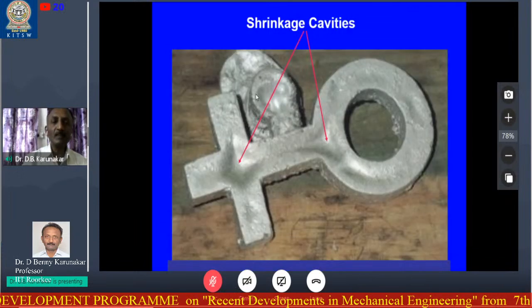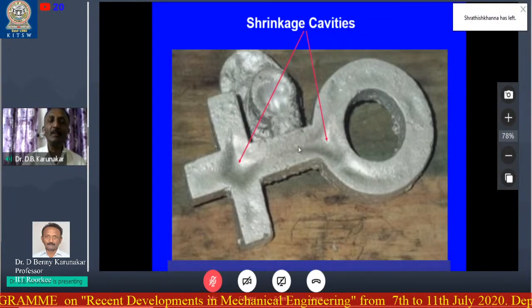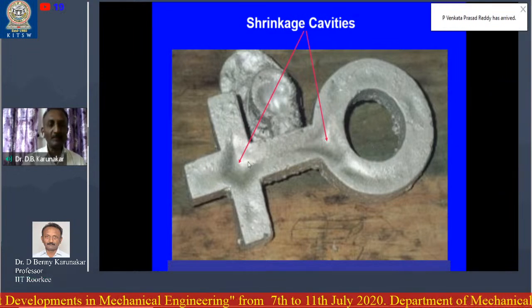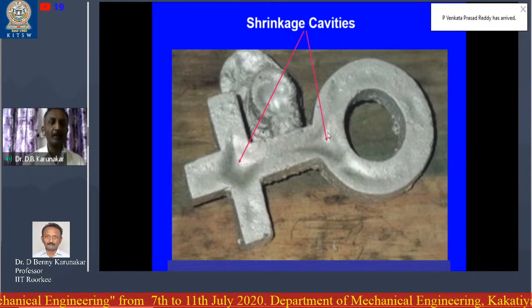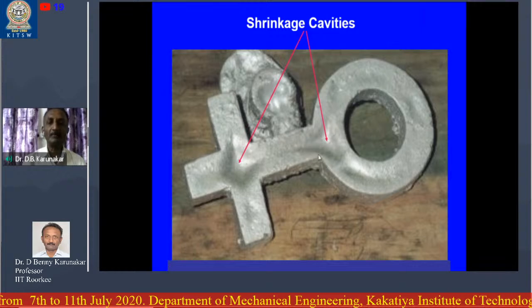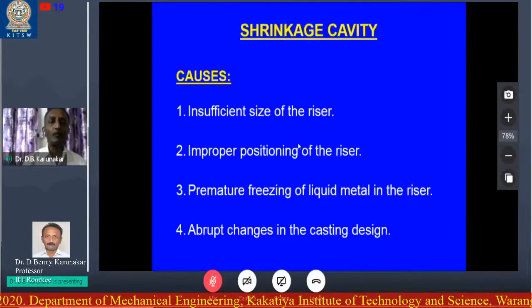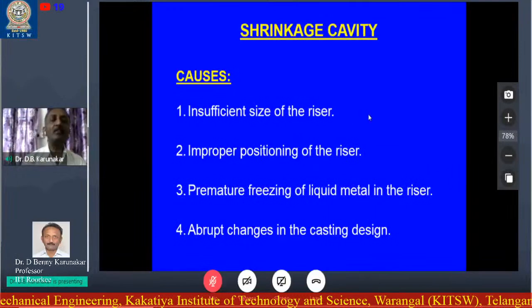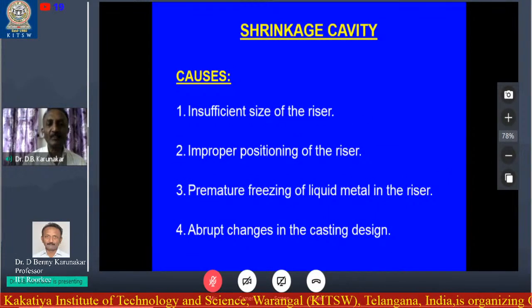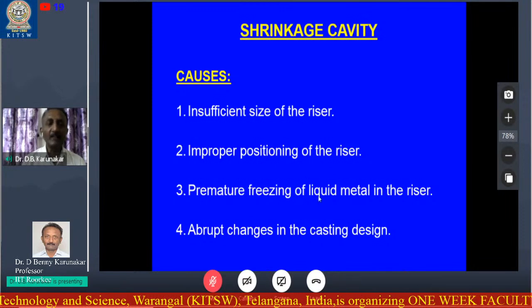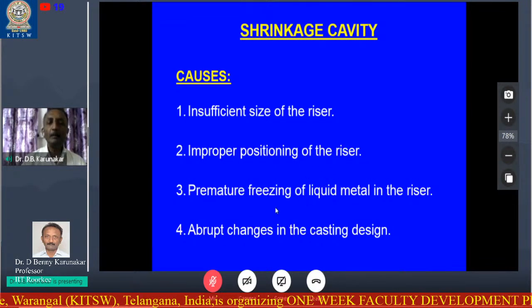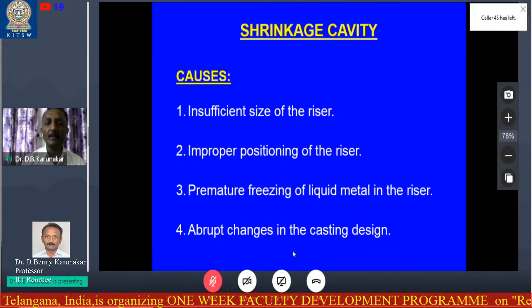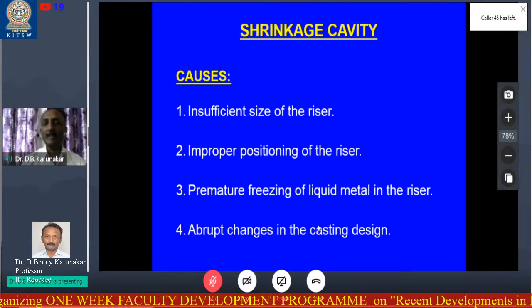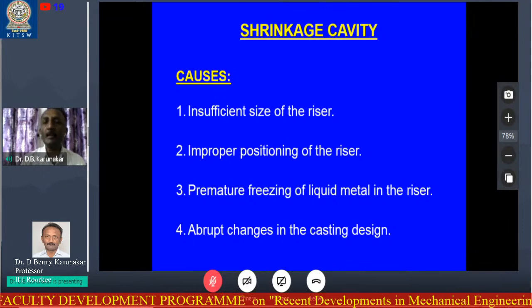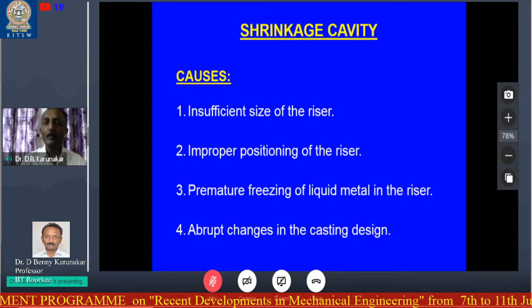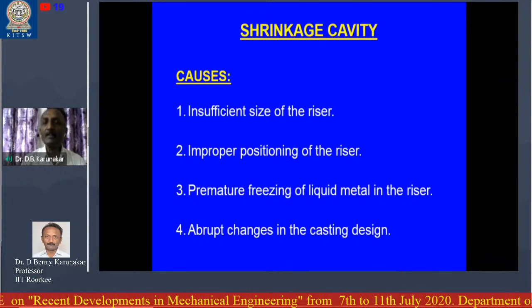Okay. Now, you see, this is a casting where there is no riser. Now you see there is a shrinkage cavity. So here is a shrinkage cavity. Now the causes: insufficient size of the riser. That is the first reason for the shrinkage cavity. Improper positioning of the riser, premature freezing of the liquid metal in the riser, abrupt changes in the casting design. So these four factors are responsible for the shrinkage cavities in the castings.